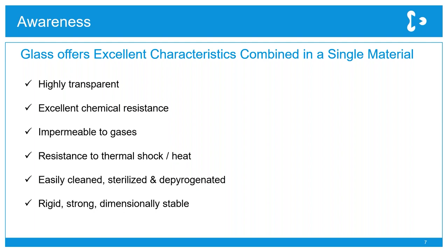Glass has some great characteristics, all combined in one single material, and that means you can use one container for many purposes. It's highly transparent, and that's probably the reason that it was used by alchemists, because they could see what was happening in the container, and you could see gold being formed from lead. It's got excellent chemical resistance, and so it can be used with pretty much any chemical without concerns, although there are some exceptions. It's impermeable to gases, which is very important to some applications in chemistry, where you have materials that are sensitive to some gases.